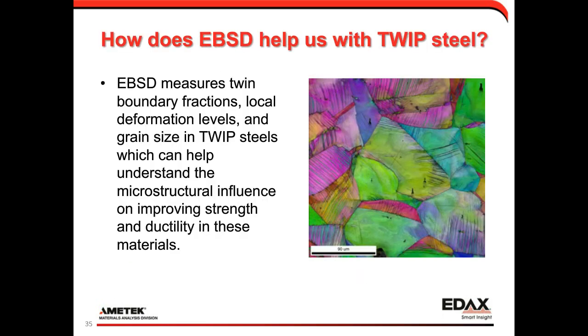So we can conclude this little section by asking, how does EBSD help us with TWIP steel? Well, EBSD can be used to measure the twin boundary fractions, the local deformation, and the grain size, which can help us understand the influence microstructure has on improving the strength and ductility of the materials.